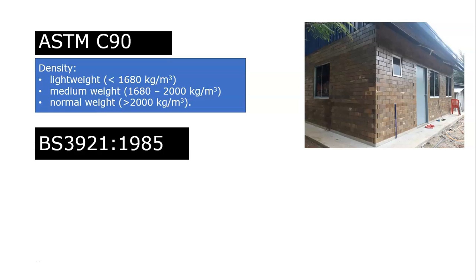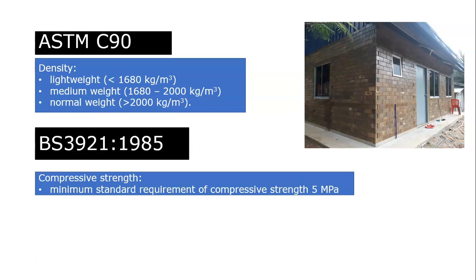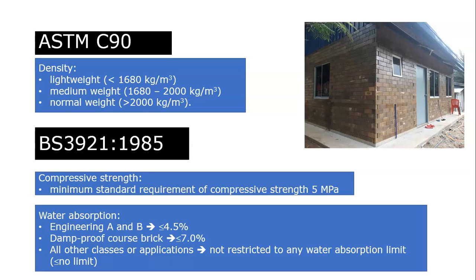And according to BS 3921 1985, the minimum compressive strength for brick is 5 MPa. Meanwhile, the water absorption limit is specified that for engineering A and B, the water absorption is less than or equal to 4.5%. For damp-proof course brick, the absorption is less than or equal to 7%. Meanwhile, bricks for all other classes or applications than those mentioned above are not restricted to any water absorption limit.